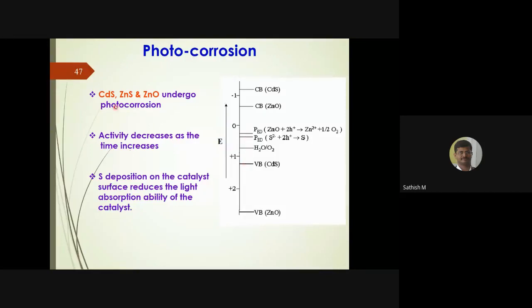For example, I told you zinc sulfide, zinc oxide and cadmium sulfide are very corrosive in nature. But let us just take zinc sulfide, and not worry about other things. The valence band of zinc sulfide is here. The conduction band of zinc sulfide is here. As I told you, this energy gap is only 2.5 or 2.6 electron volt. This falls around 500 to 600 nanometer. So that's perfectly good for visible light photocatalysis.